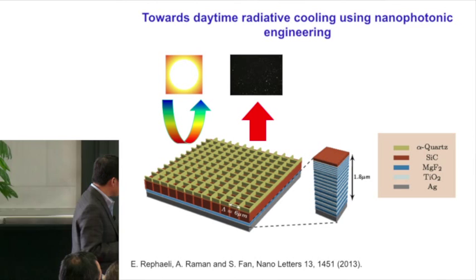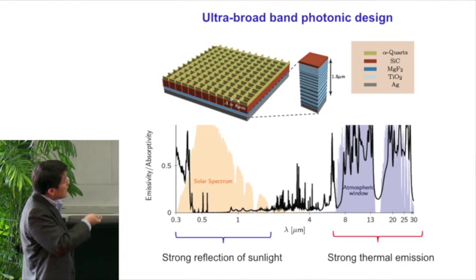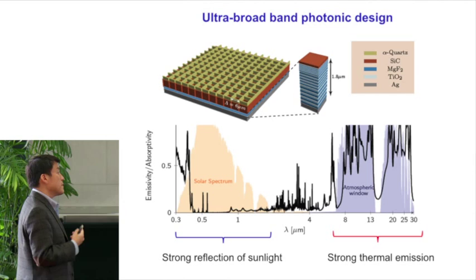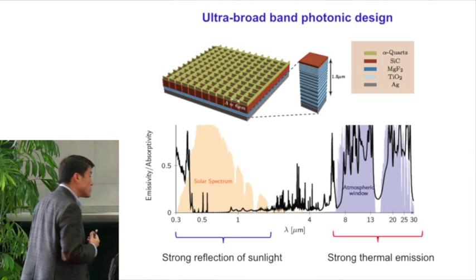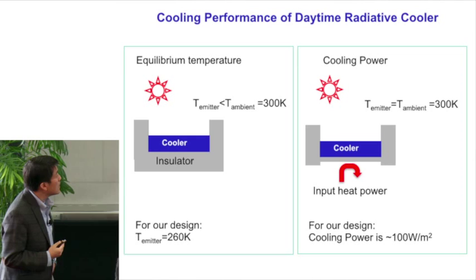And if you look at the calculated emissivity spectrum, it has very low emissivity in the solar spectral side, so that is a very good mirror, but it has strong emissivity in the 8 to 13 micron window, so it can emit heat out. With the spectrum that I show you, you can compute the cooling performance of this device.